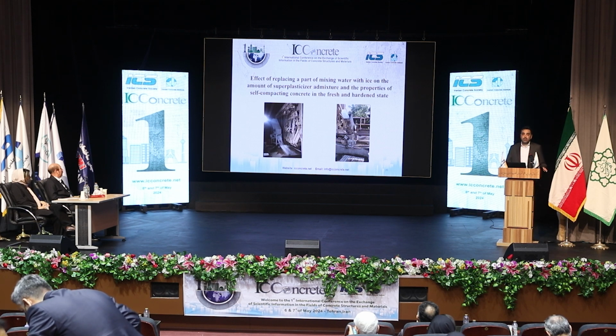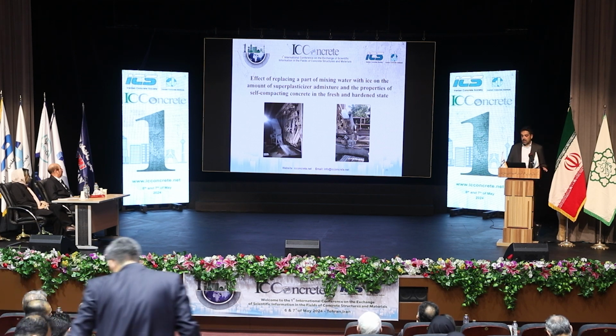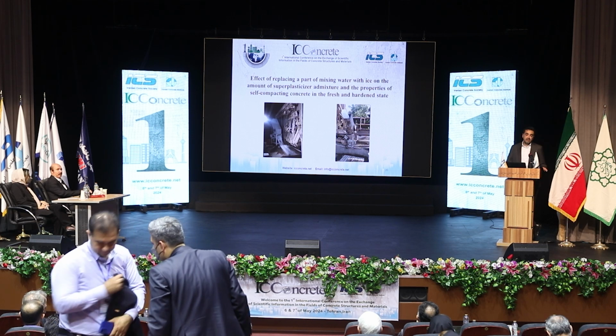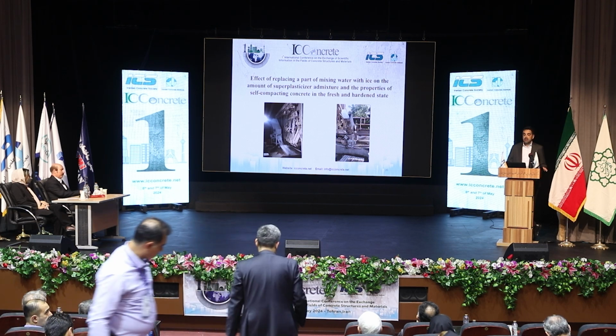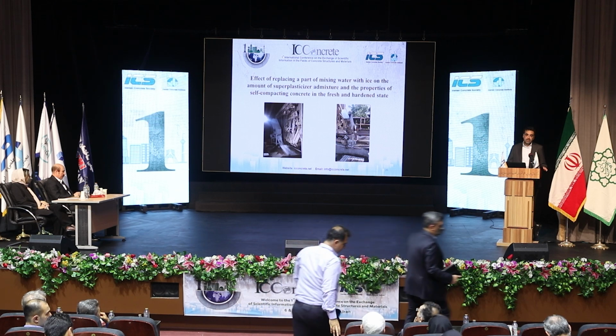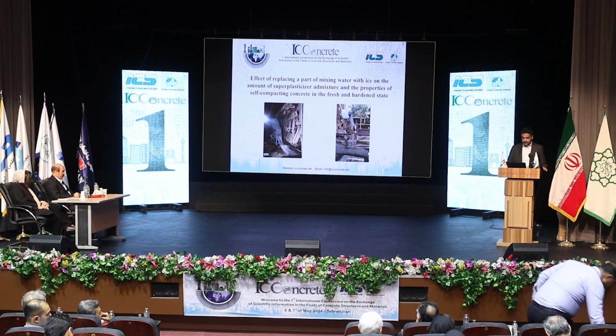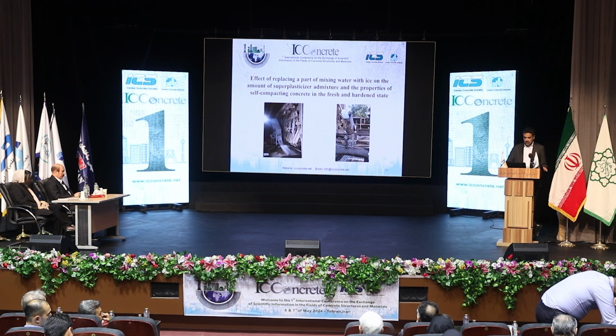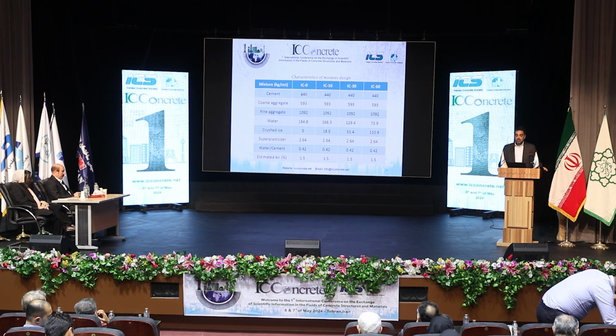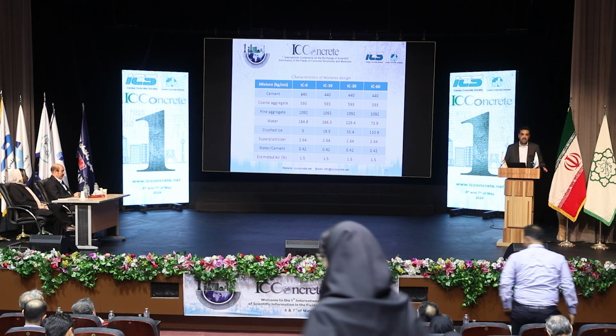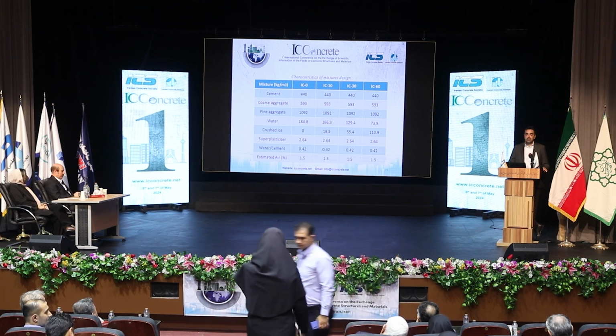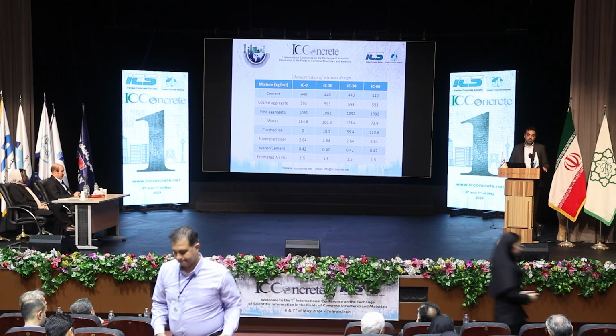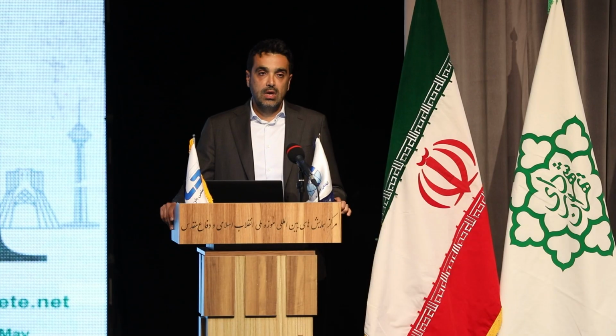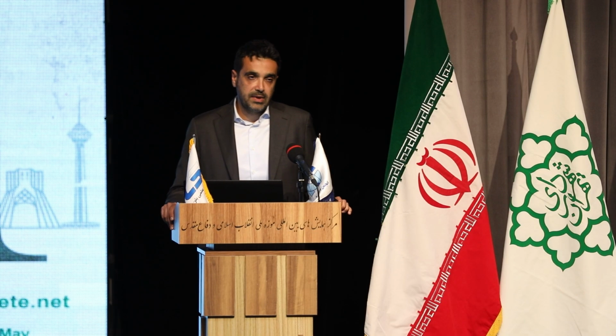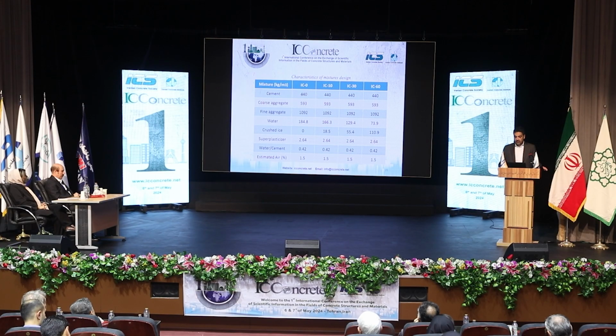In another work, we tried to evaluate the effect of using crushed ice on the properties of self-compacting concrete and its price also. For this purpose, we made 4 mixtures totally. All the mixtures were the same. The only difference was the amount of water replaced by crushed ice, and also the dosage of superplasticizer was different.